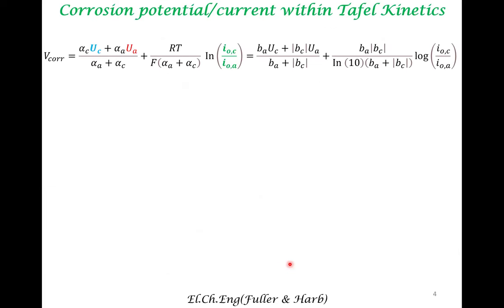So moving on further, if you know the equilibrium potential corresponding to the cathodic reaction, the equilibrium potential corresponding to the anodic reaction, and these quantities which have been defined in previous lectures on electrochemical kinetics, and the exchange current densities corresponding to the cathodic reaction and the anodic reaction, there is an analytical formula for corrosion potential, assuming the kinetics obeys Tafel kinetics. So you need to know all these quantities to get the corrosion potential.